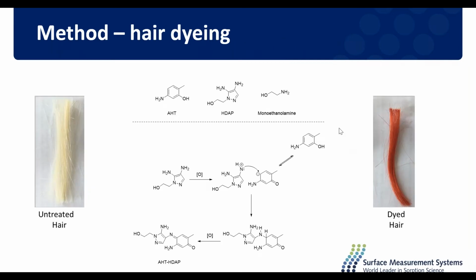We also dyed hair, because dyeing hair involves hydrogen peroxide, and this oxidizes disulfide bonds. So we're still getting disulfide bond breakage, but we wanted to examine a different type of damage. All the other additives from the hair dye solutions and formulations will also interrupt some electrostatic bonding within the fibre, leading to more disorder in the hair. And so we wanted to examine how that would affect our water sorption properties.